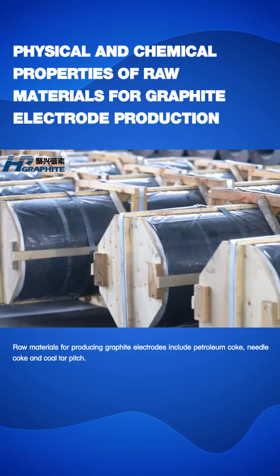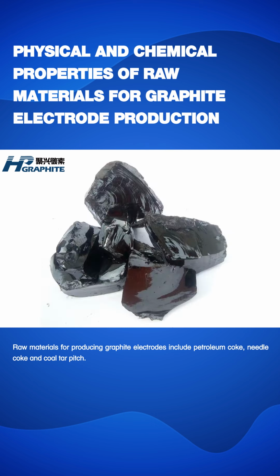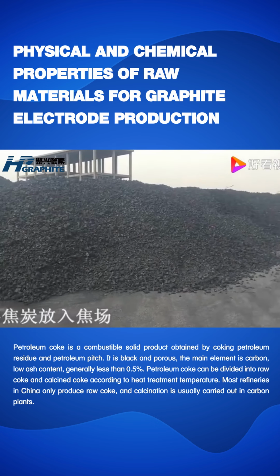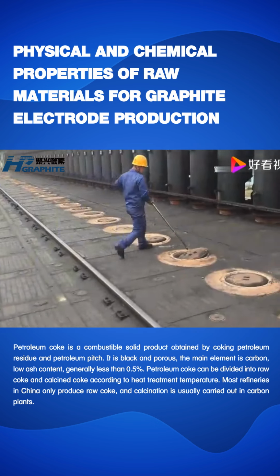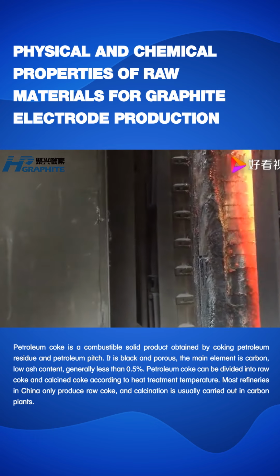Raw materials for producing graphite electrodes include petroleum coke, needle coke and coal tar pitch. Petroleum coke is a combustible solid product obtained by coking petroleum residue and petroleum pitch. It is black and porous. The main element is carbon, with low ash content, generally less than 0.5%.